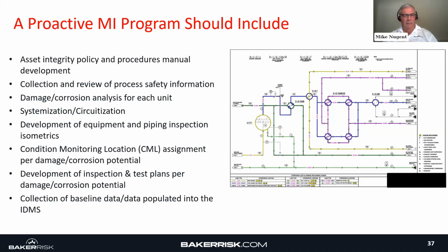We're trying to move away from the time-based inspection, which says every 5 years I'm going to go out and take thickness readings. Some of the corrosion mechanisms that we deal with can happen in the space of a shift in a plant, which is 8 hours to 10 hours. Certain stress corrosion cracking methods, if you put in the wrong bolts, by the time you walk around at the end of your shift to look at that, they could have cracked and fallen out.